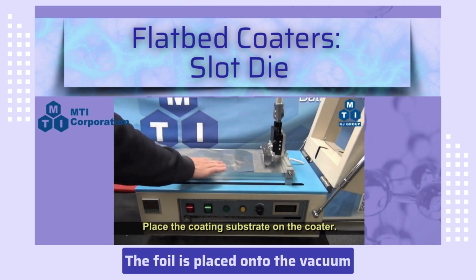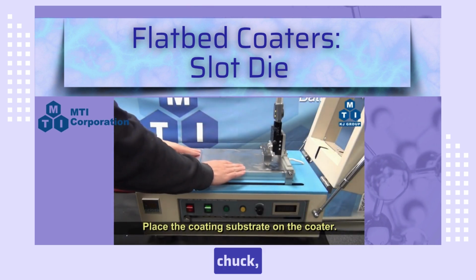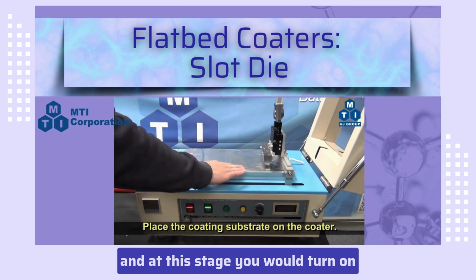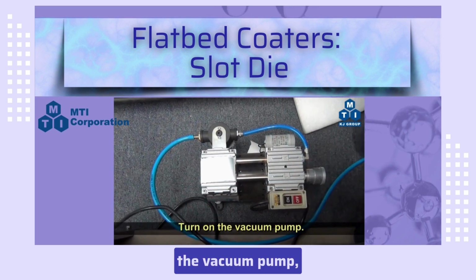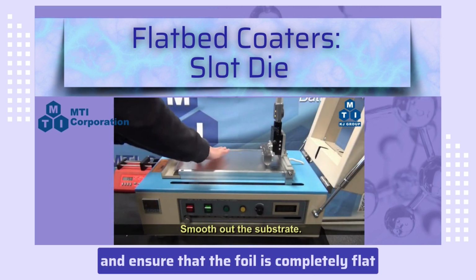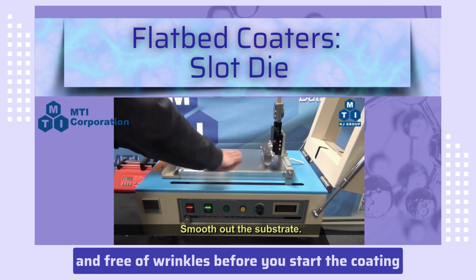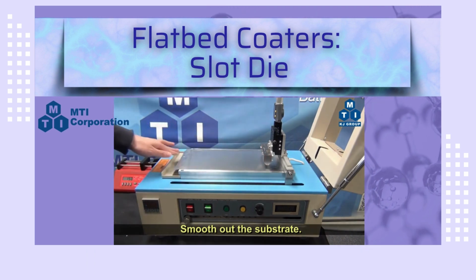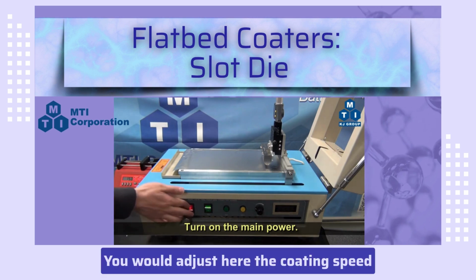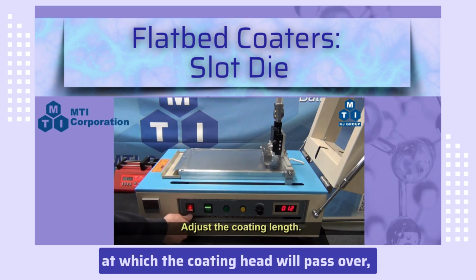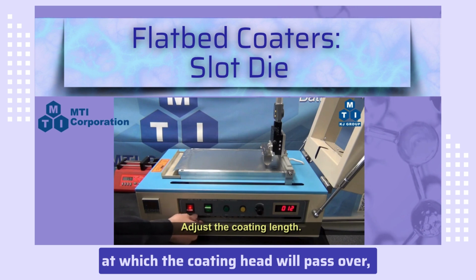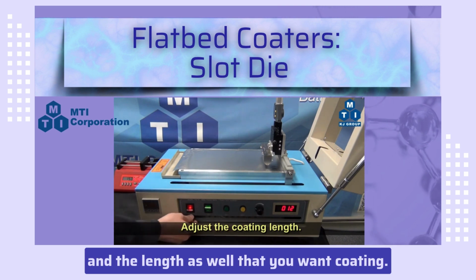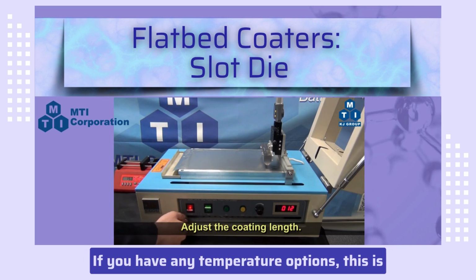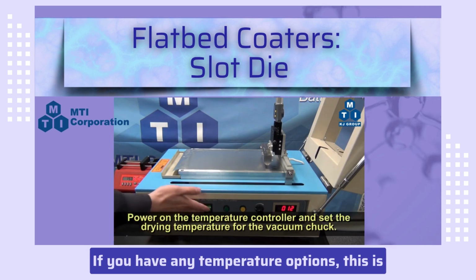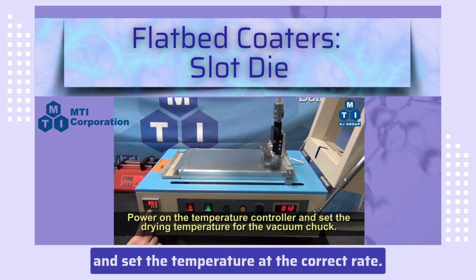The foil is placed onto the vacuum chuck, and at this stage you would turn on the vacuum pump and ensure that the foil is completely flat and free of wrinkles before you start the coating process. You would adjust here the coating speed which the coating head will pass over, and the length that you want coating. And if you have any temperature options, this is where you would turn these on and set the temperature at the correct rate.